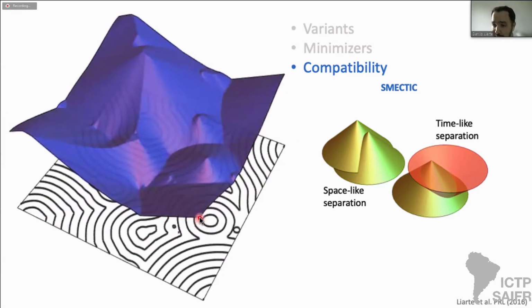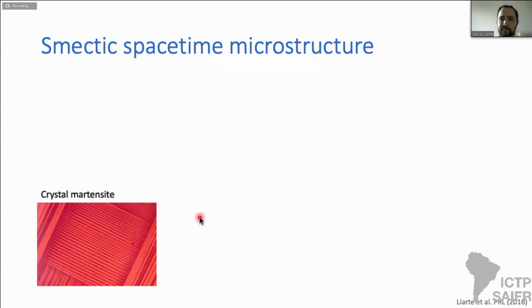What I'm going to do next is to use computational tools to decompose this smectic section into domains corresponding to different variants. Here's the crystal Martensite that I showed before. You can interpret the light red as variant 1 rotated by a certain angle, and dark red as variant 2 rotated by a different angle. And then there is a very interesting mathematical analysis that you can use to explain all these fine laminate structures.